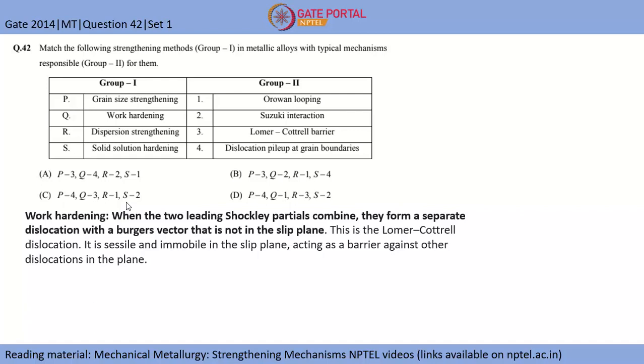So if that occurs, this dislocation, which is the combination of these two Shockley partials, cannot move because that is not the slip plane in FCC. So this forms a sessile dislocation. Sessile dislocation means the dislocation cannot move. Hence, if this dislocation is present in a material, it will cause trouble for other dislocations which are easily gliding. So this is known as the Lomer-Cottrell lock. And as this is a sessile and immobile dislocation, it acts as a barrier for other gliding dislocations in that plane. Hence the work hardening which we are seeing is basically because of the Lomer-Cottrell barrier. So the correct answer for work hardening is option 3, Lomer-Cottrell barrier.